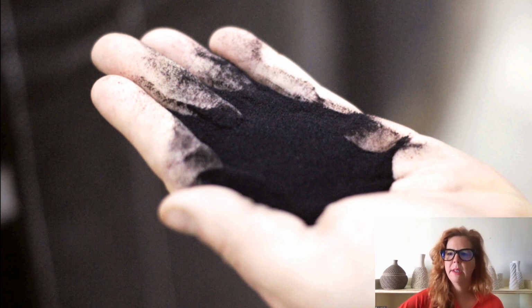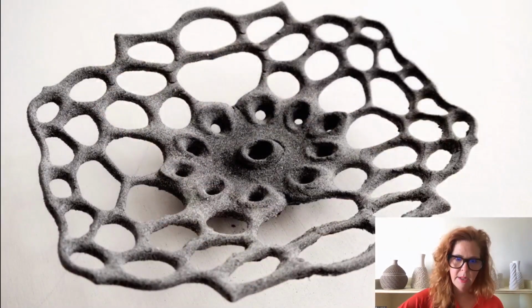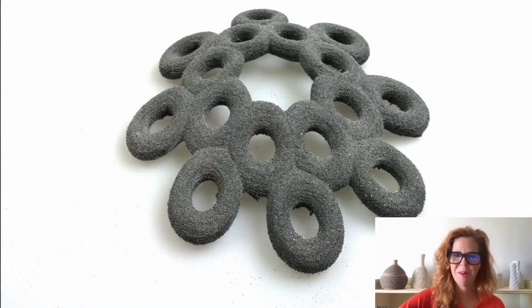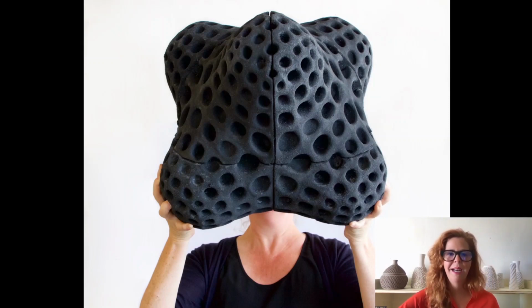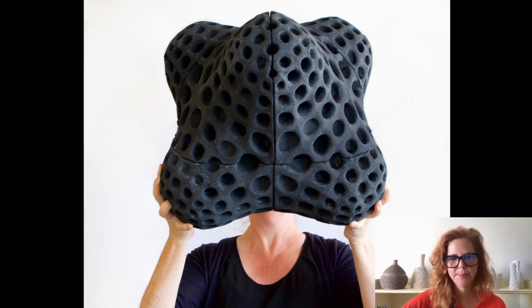The tires are frozen, reduced to crumb, and then ground into a fine mesh, which is typically used in roofing or asphalt pavement. And we're able to 3D print with this material. And we have slowly been able to perfect this formula to make a more refined finish. And imagine the possibility of using it to create furniture such as this rubber poof, which one could find outside, maybe at playgrounds or bus stops, and other exterior materials or applications for this material, I should say.